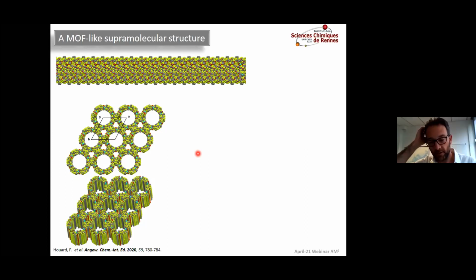Yeah, sonocrystallization is very useful to have powders with high purities, but obviously since you are sending sonication waves in your crystal, you cannot grow very big crystals. We see a limit after 3 hours of sonication, we have a plateau that depends on each system. And these are still crystallites that you can see on AFM. These are all AFM images, but they are not big enough to be considered for single crystal measurement. Okay, thank you.